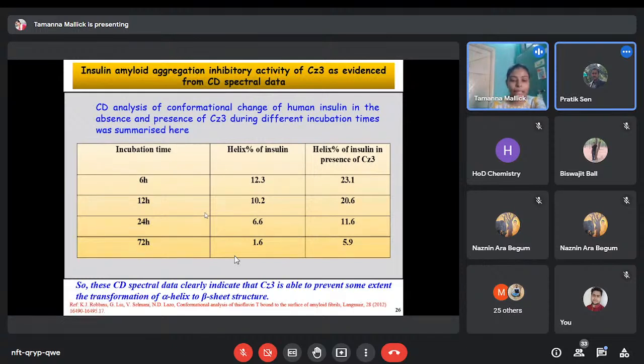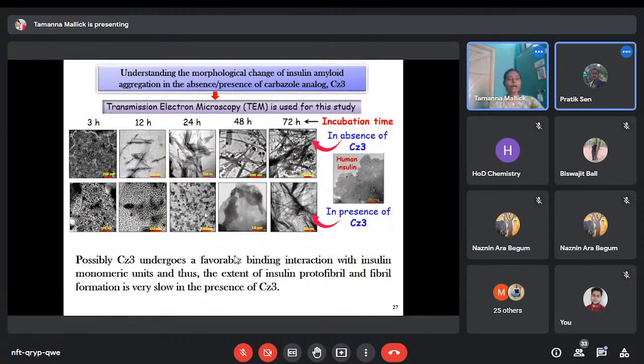Hence, the CD spectral data clearly indicate that CZ3 is able to prevent, to some extent, the transformation of alpha helix to beta-sheet structure. Now, to understand the morphological change of the insulin amyloid aggregation in the absence and the presence of carbazole analog CZ3: in presence of CZ3, few aggregated parts were observed, and the morphology closely resembled the human insulin. But in absence of CZ3, very densely packed fibrillary structures were observed. This is probably because CZ3 undergoes a favorable binding interaction with the insulin monomeric unit.